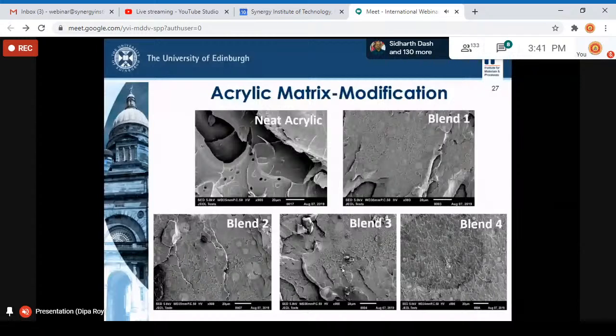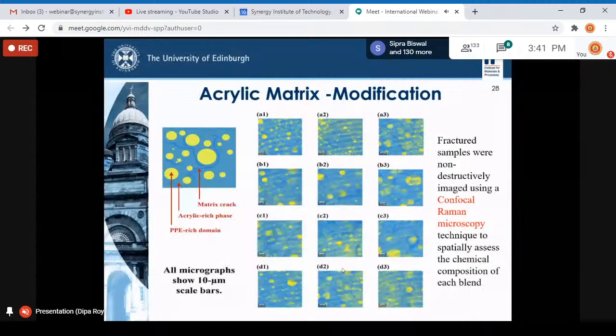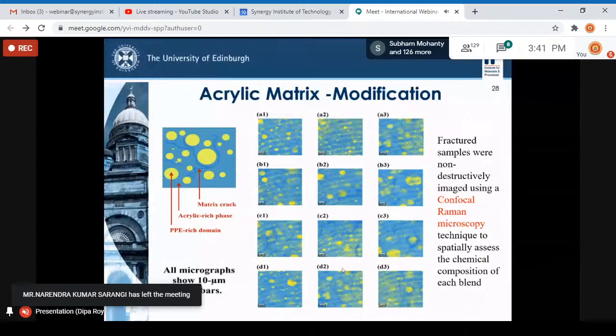So now we selected, okay, this is another micrograph. This was generated by confocal Raman microscopy. Here the blue phase is the acrylic phase and the yellow phase is the polyphenylene ether. So we can see how more or less uniformly this polyphenylene ether is dispersed in the acrylic matrix. We also tried to understand the chemical composition by Raman spectroscopy, but we haven't yet completed those tests or analysis. That's why I haven't included that in my presentation. But overall, this gives a very clear picture of how the polyphenylene ether is dispersed in the acrylic matrix.